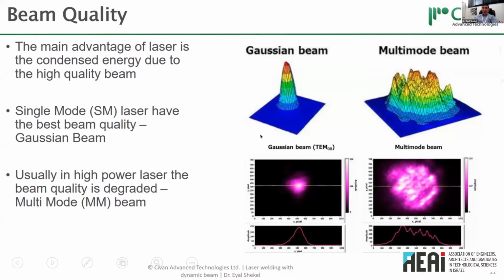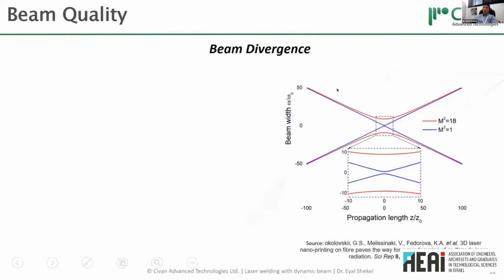Usually, when you go to high power lasers, the beam quality is degraded because you have to take a lot of power and concentrate it in one place. And we'll talk about it in a few slides. But basically, the difference between a single mode beam and a multi-mode beam has two effects. First of all, with a single mode beam, you can get a much smaller spot. So if you start with the same aperture with a multi-mode beam, which is the red here, compared to a single mode beam, you can see that the single mode beam can have a much smaller spot size.